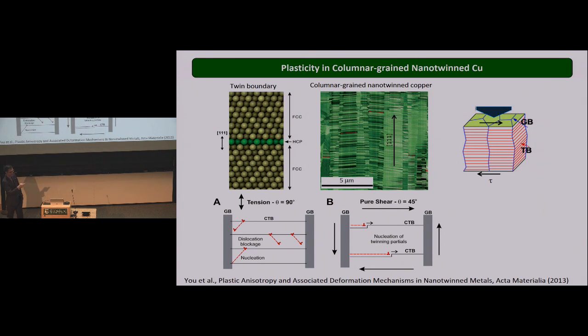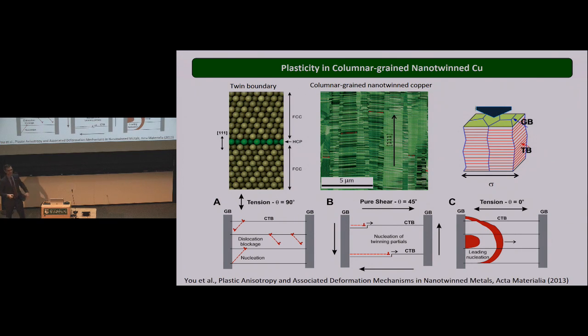All right. And then the more practical test is actually to take the film and simply perform a tensile test on the film. In this case, what you expect to produce is called a threading partial. It's like a dislocation that runs parallel to the direction of the film. And it turns out that based on theory, if there's nothing blocking the dislocation, the twin boundary in this case plays no role.